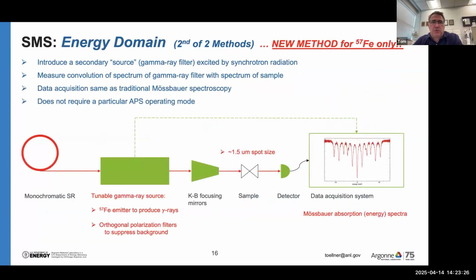For the case of iron-57, we will do an energy domain approach. This is a new approach that the other synchrotrons also offer. Our approach is a little bit different than theirs, but in the end, it's still going to generate a Mössbauer absorption spectrum. This requires that we introduce a secondary source, a gamma ray filter, if you will, that generates gamma rays that have some neV of line widths. At the same time, it has to get rid of all the non-resonant radiation, which would contaminate an absorption spectrum.